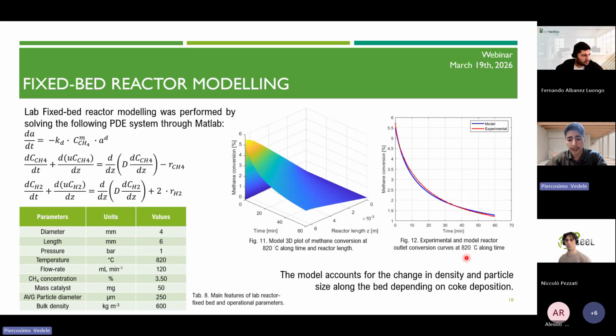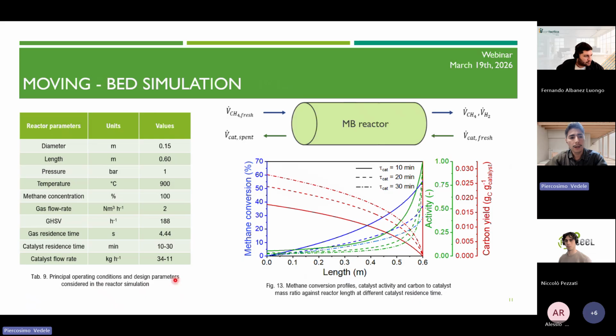the deposition of the carbon, but of course the conversions are really small, and also the methane concentration is really small, so the amount of carbon deposited is small, and we don't have a huge change in density and particle size, but it is taken into account. Those results were useful also for a simulation of a new kind of reactor for conducting this kind of reaction, a moving bed, where gas and solid are sent to the reactor countercurrently.